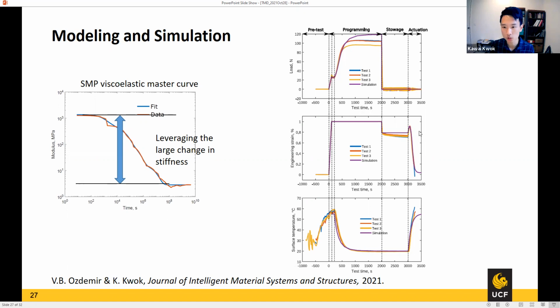And so you can see that there is the simulation, which is the purple curve, and then all the other tests. This is an extension experiment, so it's easier to manage. But we have all the thermomechanical interactions incorporated in the model. We're able to capture the actuation pretty well. The only thing that we cannot quite capture exactly is that there's still some sort of relaxation, some sort of deformation change when the material is in the frozen stage, the programmed configuration. This is related to what I was saying, that it tries to go back to the original shape, and it does in some amount. But there are more details in this paper we just published on this idea.